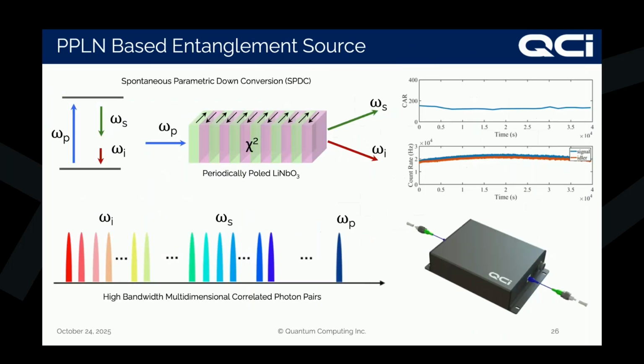Going back to the PPLN-based structures, we do currently make periodically poled lithium niobate-based entanglement sources in-house. The bottom right image that you see is an actual product that we have available for sale that is based on bulk lithium niobate. So we do the PPLN, we pole the bulk lithium niobate, and we are able to get entangled photon sources out of it in a very stable format, as you see, and with a very stable count rate that you can see in the graphs over there.